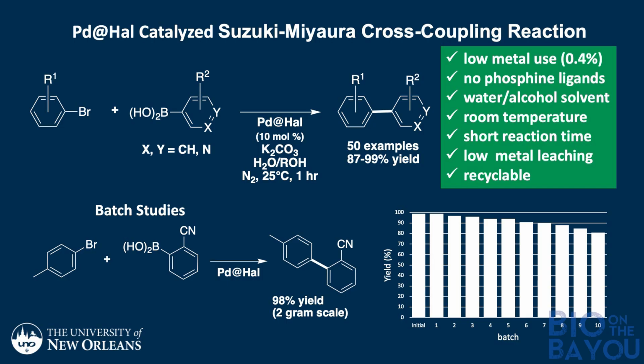Now, we extended this chemistry to that losartan building block, and we found that we could make this building block in 98% yield on a 2-gram scale. But more importantly, we found that we could take the catalyst, filter it off, and then add it to another system and repeat. And in the next batch, we didn't lose any activity. We could take the same material and keep recycling it again and again. And essentially, it wasn't until the 7th or 8th time that we saw yields start to diminish. So this greatly extends the lifetime of the catalyst and the utility of the process.